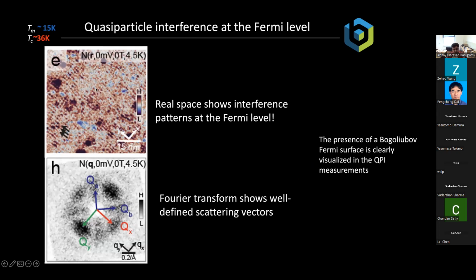And if you do that, so here, this is a real space interference pattern. I hope all of you can see that there's very clear patterns that are present in real space in this material. And again, this is at the Fermi level, where a simple superconductor will not have any excitations present. If I take a Fourier transform of this, you can once again see very, very clear spots present. And what this says is a very simple message: since there are interference patterns, well-defined scattering vectors, this means that there are quasiparticle excitations in this material at the Fermi level.